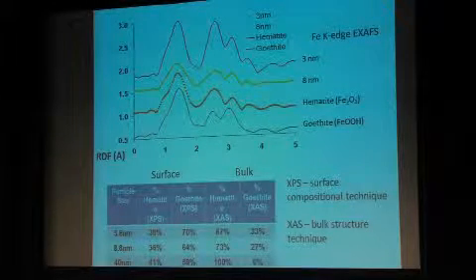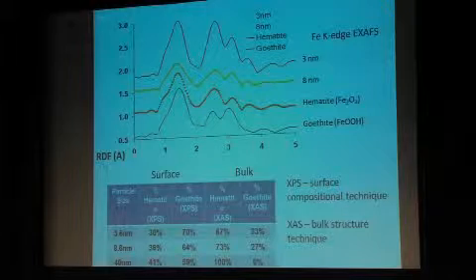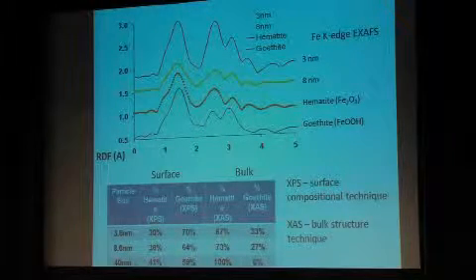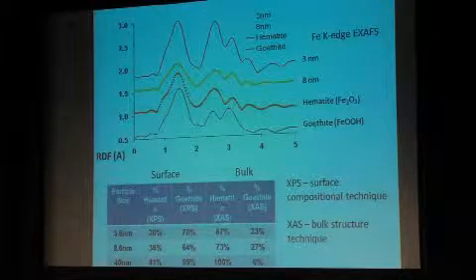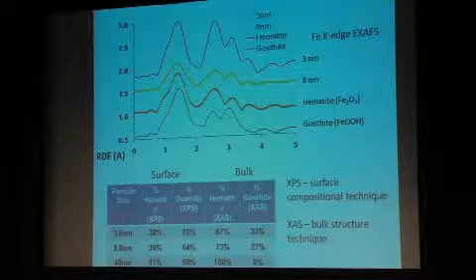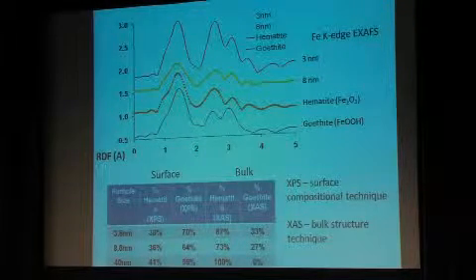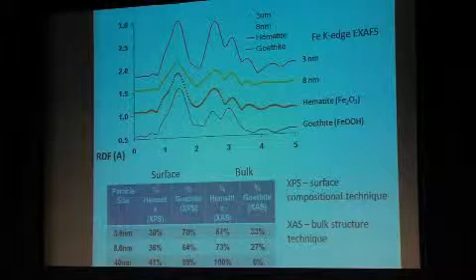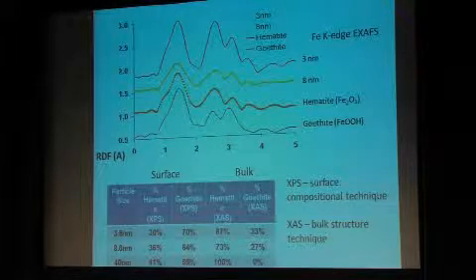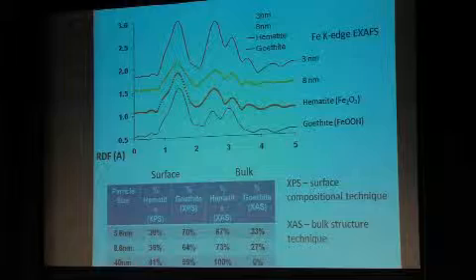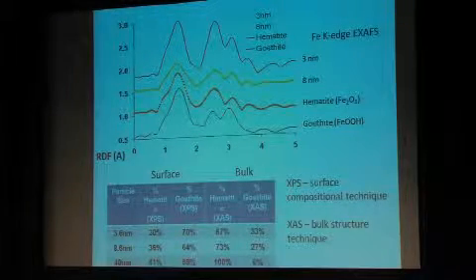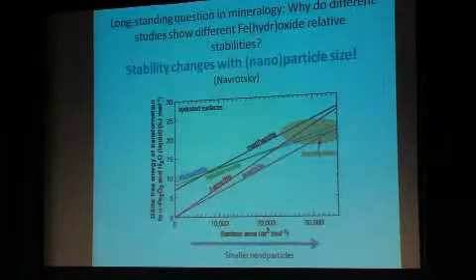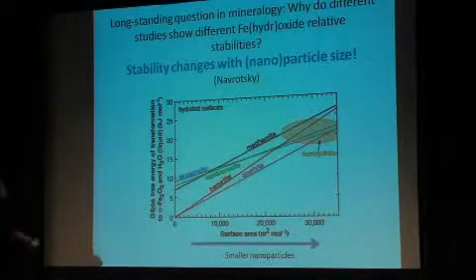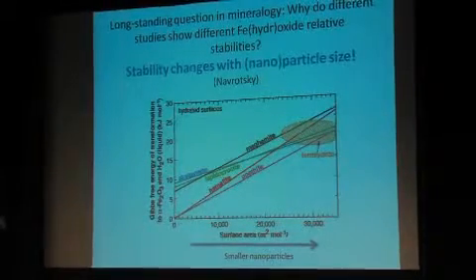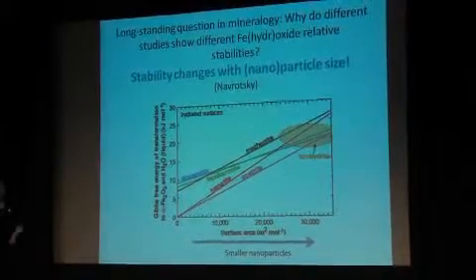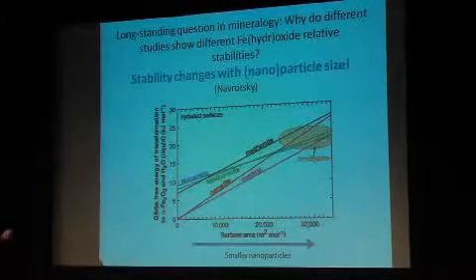So again, this has a profound impact on how things react. Because even though if you measure it by X-ray diffraction, which is the technique everyone has used since geology existed and an X-ray diffractometer was made to say what minerals are present here, it only picks up the hematite. But in fact, these tiny, tiny particles have a more hydroxide structure, especially at their surface. Why does this matter? Well, one reason why it matters is because it changes the stabilities of the particles as they go down in size.